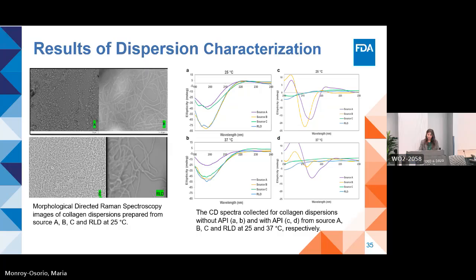So in this slide, I'm showing the dispersion characterization results that were performed using morphologically directed Raman spectroscopy to observe the fibrillar morphology in the dispersions due to the effect of the manufacturing process. On the left side of this slide, you can see the macroscopic images of A and C showing a similar kind of fibrillar aggregates. The difference is that collagen A is a little lighter in density compared to collagen C, which is very dense. However, the A and C collagen dispersion fibrillar networks are totally different from collagen B and RLD, which show a similar tangled, string-like fibrillar network in the collagen dispersion.